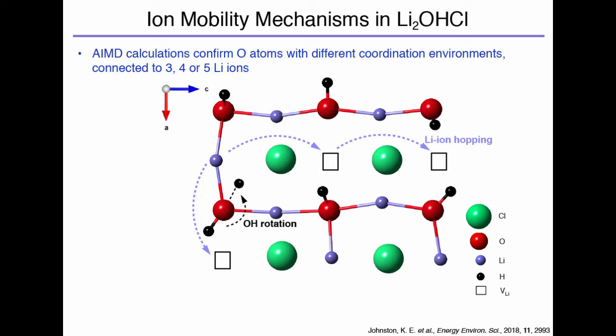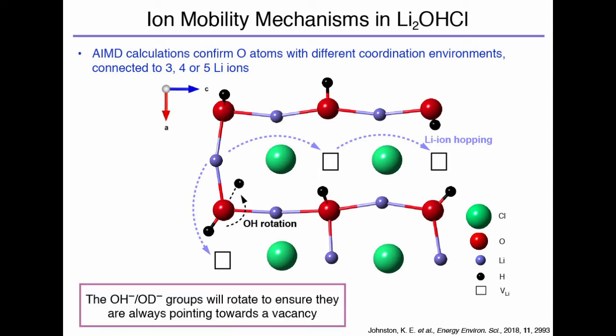So at lower temperatures, or just after the phase transition, you're going to have a few lithium ions hopping here and there, but the majority are still going to have static OH groups, or locally mobile groups. But as you increase the temperature further, you're going to have more and more lithium ions hopping, so you're going to have this constant rotation of the OH groups between a vacancy and being filled. Essentially, the thing we've discovered is that this OH group will always rotate or move to try and compensate where the lithium has gone. So if it's filled a vacancy, it will move to always point towards a vacancy. And that fits, if you remember, I said that in the cubic phase, when James and Seifel did the calculations, the OH groups were randomly oriented, and it turns out they're always randomly oriented towards a vacancy, if you look back at the data.